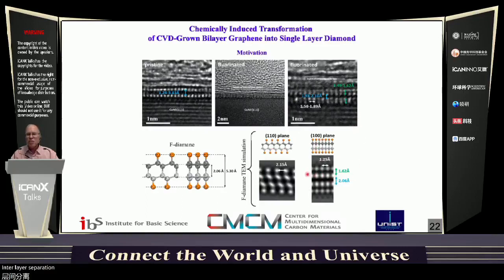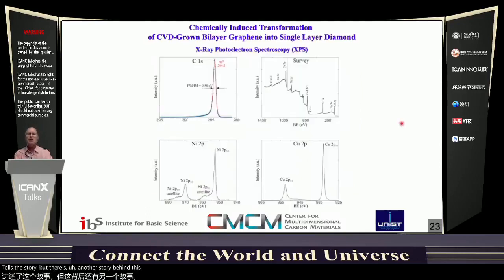The interlayer separation between the corrugated carbon layers, because they're kind of buckled up and down a little bit, is 2.06 angstroms on average. That's exactly the same interplanar spacing of planes in diamond. And the 1.62 is almost identical to the CF bond distance, for example, in the CF4 molecule or in polytetrafluoroethylene. So this beautiful cross-section imaging tells the story, but there's another story behind this, which is intimately tied in